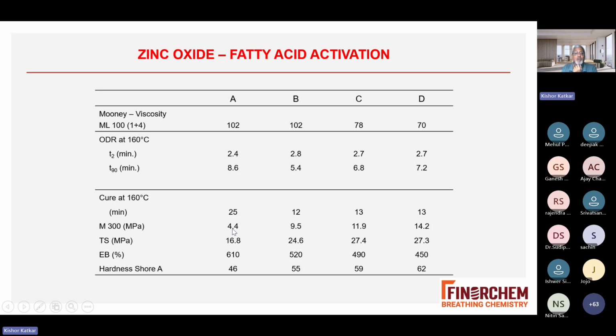The major effect is in the modulus. When there is no zinc oxide and stearic acid, even after 25 minutes, your modulus is 4.4. Then when you add zinc oxide, 9.5. With slightly lower stearic acid, 11.9. When you are using an optimum dosage of zinc and stearic acid in the case of sulfur accelerator, you get the optimum modulus as well as tensile. Obviously elongation and hardness. You can see 46 and 62, and in between you get lower hardness, lower modulus, elongation. So in a nutshell, when you are doing the formulation, proper dosages of activators like zinc oxide and stearic acid is a must.